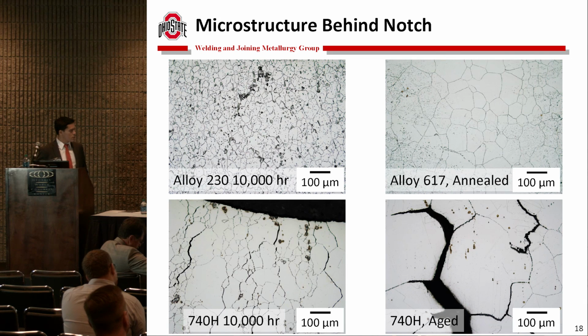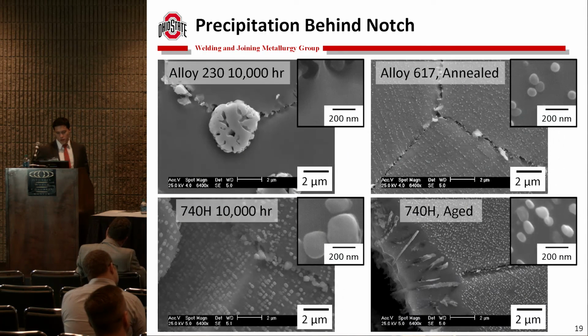This is simply a closer look at this cracking and the microstructures I just mentioned before. So this is a much clearer look at the bimodal grain size in 740H, which would have allowed more stress to be accommodated. I guess an important thing to note is that this cracking is intergranular, which is the kind of cracking I wanted to generate. So this is where it gets really interesting, in the precipitation. This is the precipitation I would expect in 617.